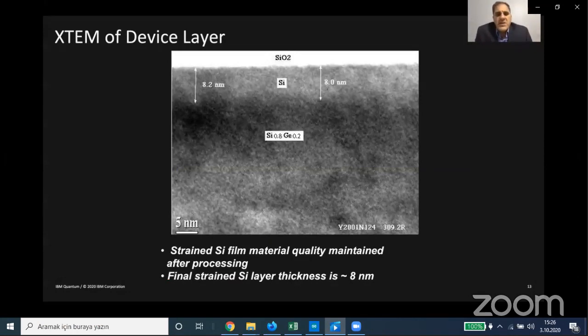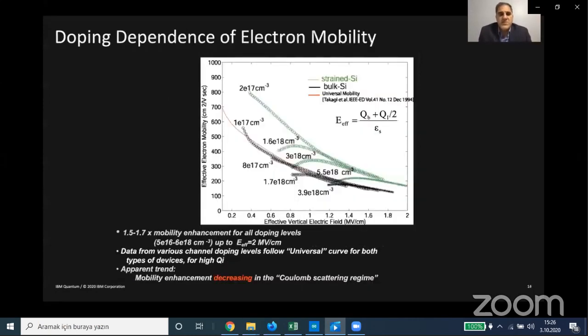In addition, the layer on top had to be preserved. As you can see here, it's very thin, around 8 nanometers. Specialized cleans had to be tailored that do not etch the material on the top. For example, the well-known RCA clean had to be modified to be at lower temperature to reduce the etch rate before gate oxidation, for example.